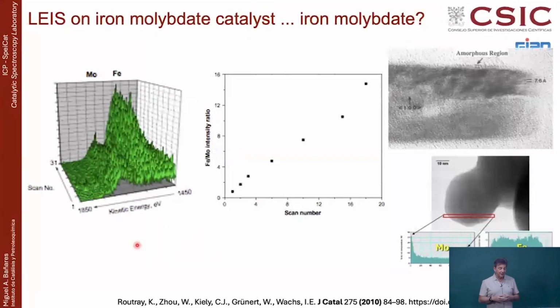And actually, we were commenting yesterday about the low energy ion scattering, that you can measure what is happening at the surface. With several scans of the iron molybdate, in the first scans you see that there is a lot of molybdenum that is more or less leveling off, but iron was not visible, and scan after scan after scan, iron becomes more and more visible. When you plot the ratio of iron to molybdenum against the number of scans, you see that the presence of iron is increasingly visible. So it means that even when this is iron molybdate, the surface is essentially molybdenum. And when you are still knocking off, say, it is iron molybdate. But at the beginning, from the outside, it looks like molybdenum only.